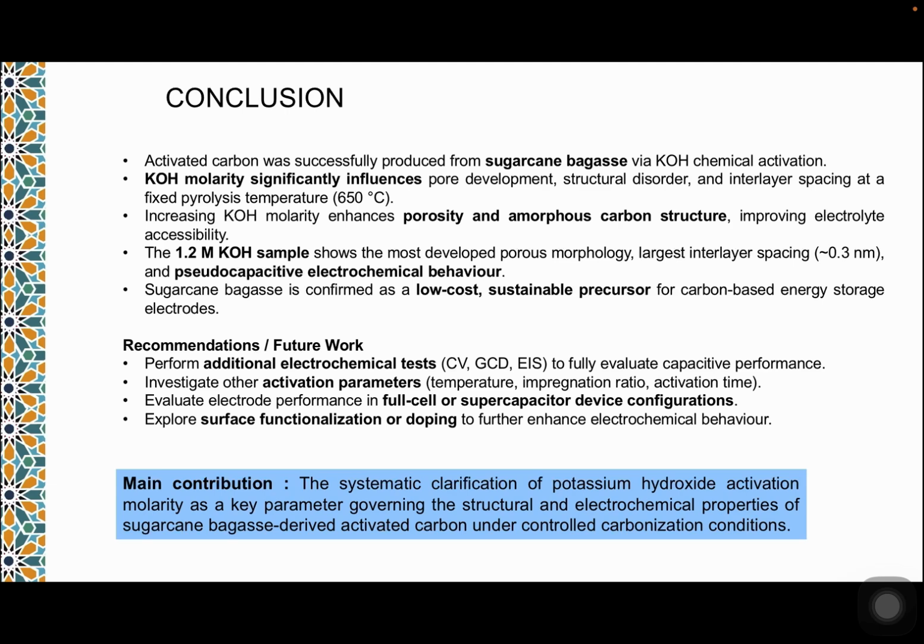The 1.2 mol KOH sample has the most developed porous morphology, the largest interlayer spacing, and also pseudocapacitive electrochemical behavior. Finally, sugarcane bagasse is confirmed as a low-cost and sustainable precursor for carbon-based energy storage electrodes.